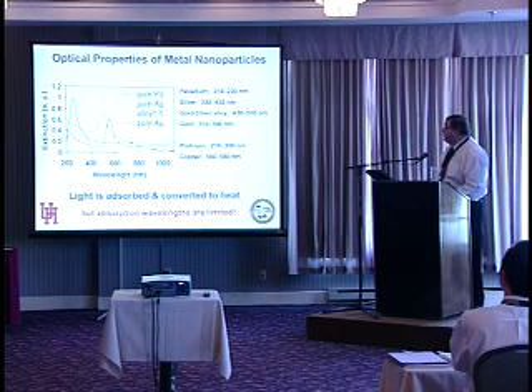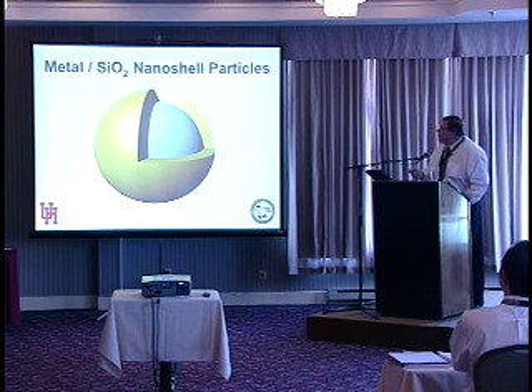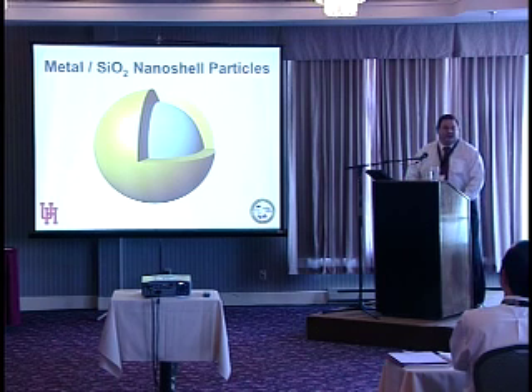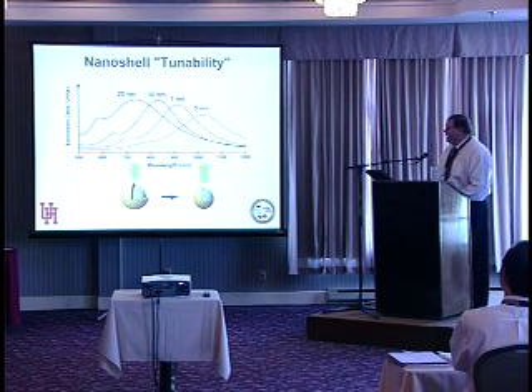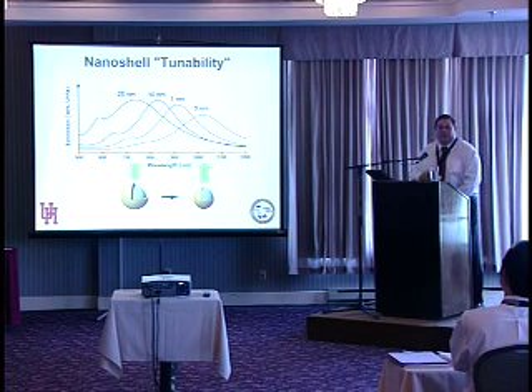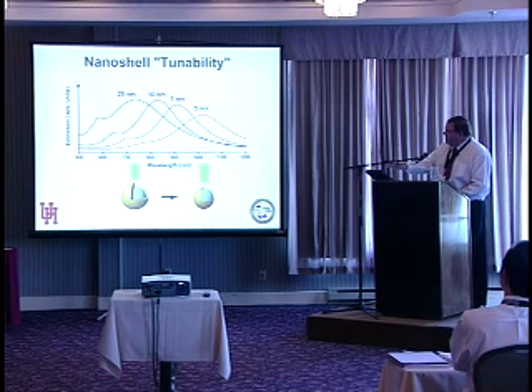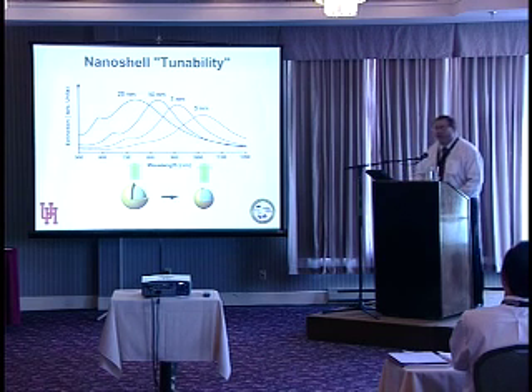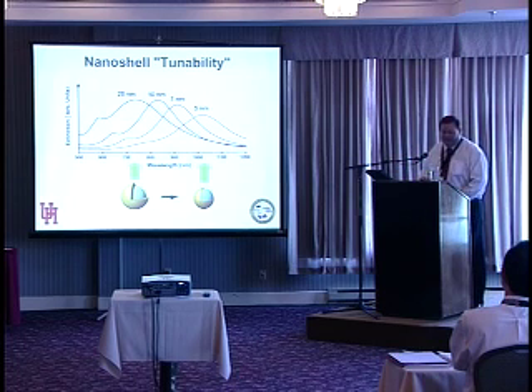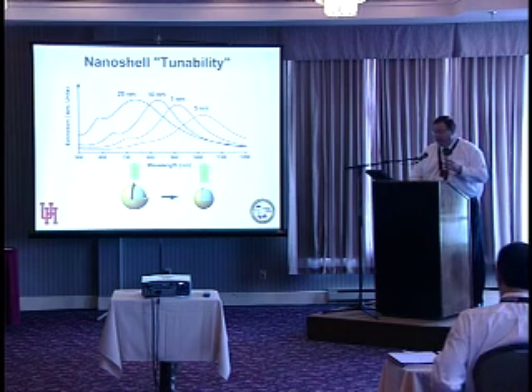Now, about 10 years ago, in collaboration with my colleagues at Rice University, we developed a nanoparticle architecture which we call a nanoshell. And if you take a silica core, a non-conducting core, and then you coat it with a metal, this gives some tunability to the plasmon resonance. So for example, if you have a 100 nanometer silica core and you coat it with a thin gold shell, where the gold shell is about 20 nanometers thick, the plasmon resonance will appear at just above 700 nanometers. And as you make the shell thinner and thinner and thinner, the plasmon resonance shifts further all the way into the near infrared. So now we can take simple metal nanoparticles, and if we put them in this architecture, we can have tunability that allows us access to the near infrared.